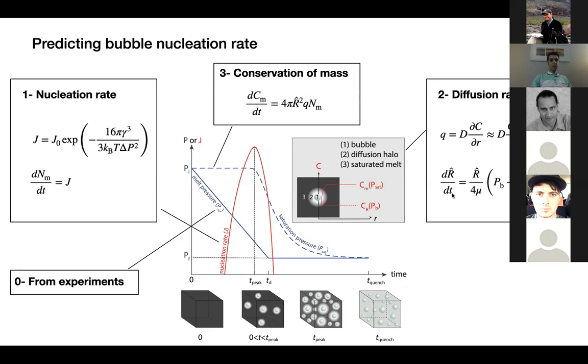Now, because it's not feasible to track the growth rate of each individual bubble in the system, we use the method of moments, first introduced by Toramaru for bubble nucleation in magmatic systems. What it does is basically track bubble growth for one bubble with the size of the average of all bubbles. So that's what we do. And then at the end, using conservation of mass, we estimate the decrease in water concentration as a function of diffusion flux and bubble number density.